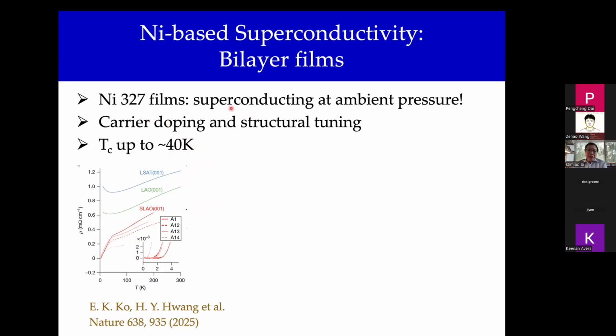range, one could work at the ambient pressure by putting these bilayer nickelates in contact with substrate in the films, and the compressive strain realizes superconductivity at ambient pressure, and these films also allow some tuning structurally. The compressed film, the strain is such that unlike pressure, the C-axis is actually elongated while the AB plane is compressed, and I'll come back to the relevancy of that to the electronic physics.